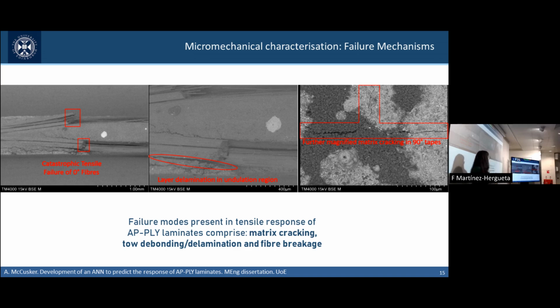Another failure mode that we can appreciate, which has been triggered mostly at the same time as fiber failure, is the delamination. So all the previous cracks that were perpendicular to the loading direction go through the tow and originate this characteristic debonding. So what we end up with is a structure where all the tows have been debonded.